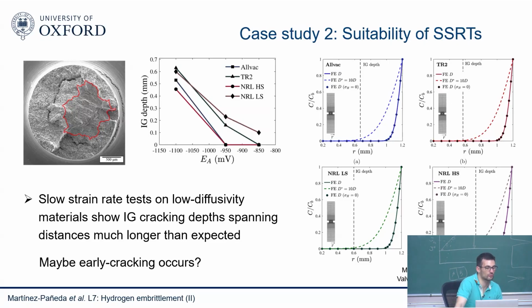Keeping track of where the crack grows is a bit more complicated. You need some DCPD and so on. So this is the simplest one, and it's very, very popular. It still is, I think, by far the most popular one. But the challenge is that in low diffusivity materials, unless you do your experiment over months, which no one does, you don't have a lot of hydrogen coming in, but you still see the embrittlement. So this is what puzzled these guys.